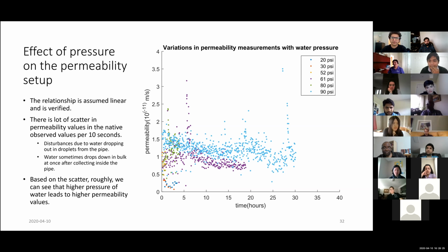And the fact that you get a higher permeability because of higher flow rate is most likely because you don't have equilibrium in these tests. Now, permeability is supposed to be a material property. What that means is your input pressure, which is really what you're looking at, 90 psi is your input pressure, right? Yeah. So to produce a greater permeability at higher input pressure, that tells you that you don't have equilibrium in these tests. Normally, you shouldn't see that, actually. If you have input equal to output, you should really get one. It will be variable, but within the same psi value, you will see a lot of variation. But that variation would not be tied to your input pressure. That's what I'm saying. If you have equilibrium, you should never see that, unless your pressures are so high. And I do see that your pressures are so high here that at 90 psi pressure, you're probably actually damaging the microstructure. Okay.